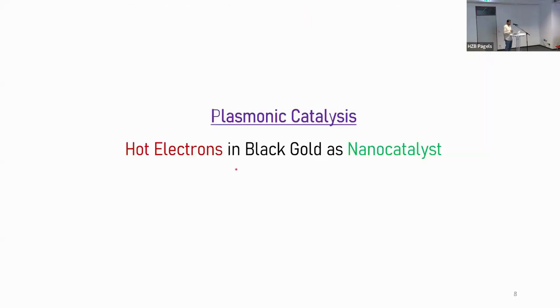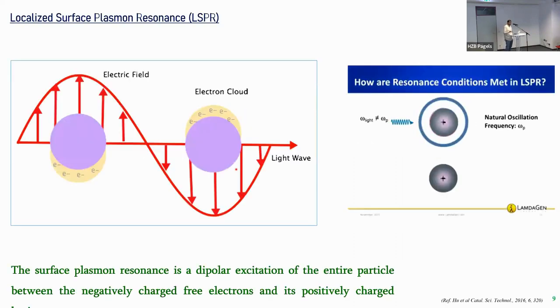So one of the concepts is using plasmonic surface plasmon resonance. I guess most of you must know it, but still, quickly, what is surface plasmon resonance? It is the dipolar excitation of the entire particle between the negatively charged free electrons and the positively charged center, right? If you consider a 10 nanometer gold particle, it has this oscillating electron cloud on the surface. And when it sees the electric field of light at one particular wavelength, there will be a resonance. And that resonance is localized onto the particle, the gold in this case, and it becomes localized surface plasmon resonance, right?